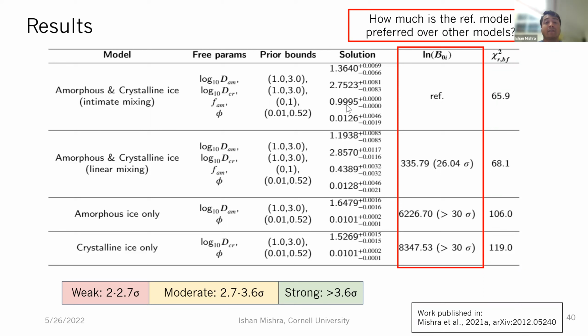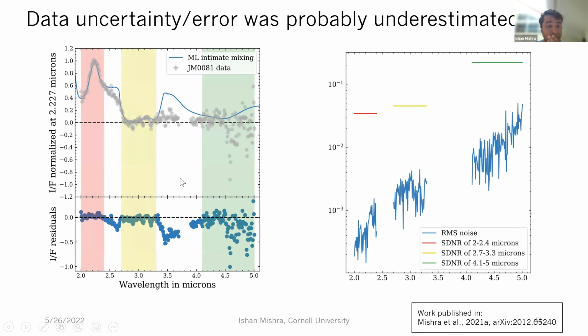These results roughly agreed with what had previously been seen, mainly that amorphous ice is very dominant on Europa's surface, especially at lower latitudes where the radiation processing is higher. Especially in the very top layers that reflectance spectroscopy probes, you get a lot of amorphization. The porosity being low is also something that has been previously seen from polarimetric studies of Europa's surface. So that was good. But one problem we were facing is that